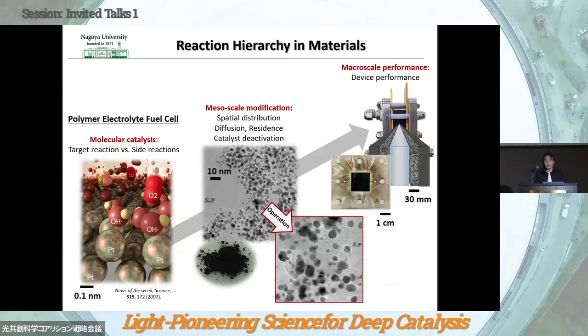However, as you know, a real material, which is a practical material, is not a single model, such as a single crystal, and has more complicated and heterogeneous structures. For example, this is an example of the polymer electrolyte fuel cell, which is composed of quite many components: electrocatalyst using a metal catalyst, carbon support, reactant, product and water, electrolyte, and gas diffusion layers in simple fuel cell systems. The main catalytic reaction is molecular catalysis, the conversion of hydrogen and oxygen to form the water molecule, providing electricity. And this kind of mechanism is widely and well investigated at the molecular scale in chemistry. On the other hand, the mesoscale reaction is a black box.